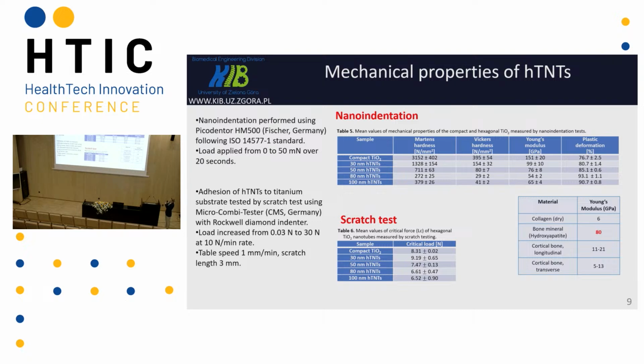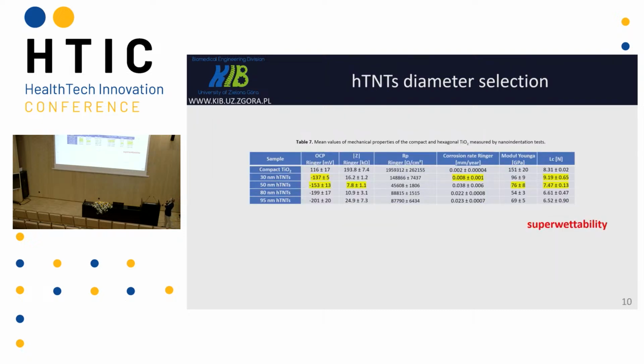Scratch test: generally the hexagonal titanium dioxide nanotubes with a very small diameter, we examined 30 nanometers, revealed a higher critical load compared to titanium dioxide. What does it mean? It means that this layer is more stable and is very solid on the implant surface, and the critical load decreases with increasing diagonal of HTNTs. So, at this stage, we were wondering which diameter or which diagonal of titanium dioxide nanotubes is preferable for implant application.